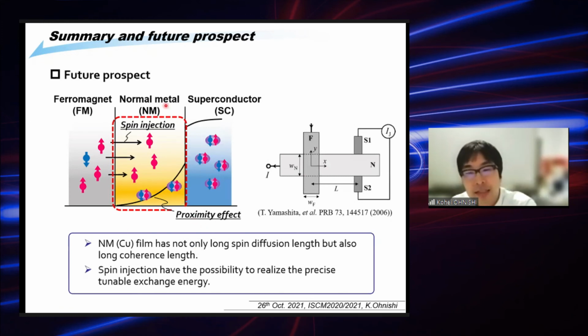In my opinion, this can be useful to explore the interaction between the spin polarization and the Cooper pairs. Because in this normal metal layer, for example a copper film, there is a long spin diffusion length and also a long coherence length for the Cooper pairs, so the structure does not need to be too thin.